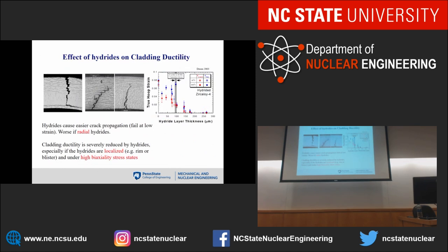When these hydrides form, they have a very big effect on the cladding ductility. Here's a cladding fractography. This is with a liner, but forget the liner for a second. You can see that the crack propagated along the hydrides, right? The same here. The hydrides were horizontal, so it goes zigzag, zigzag, zigzag, zigzag, right? When the hydrides are more or less radial, it goes zoop, a lot easier.